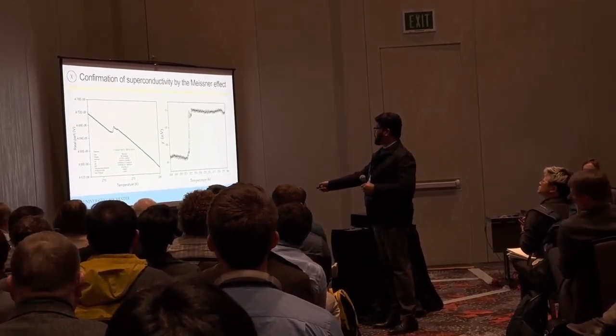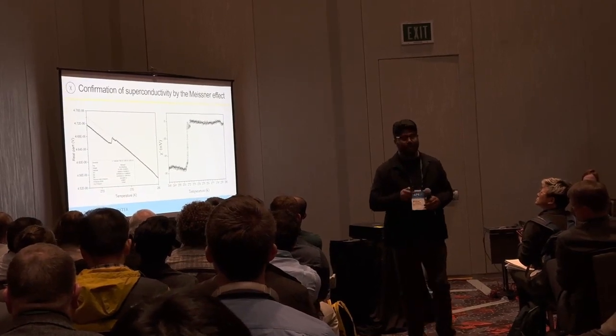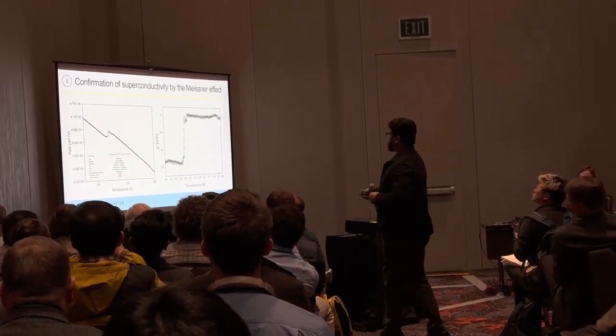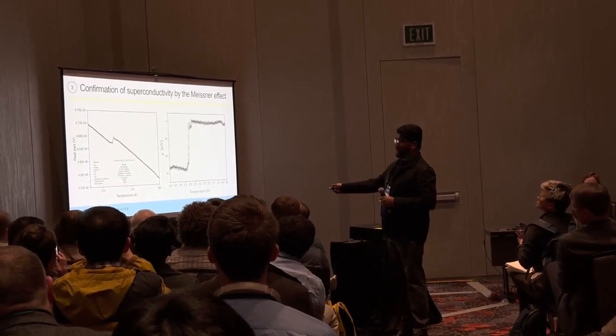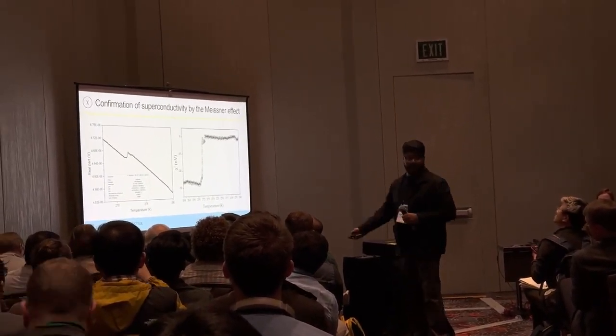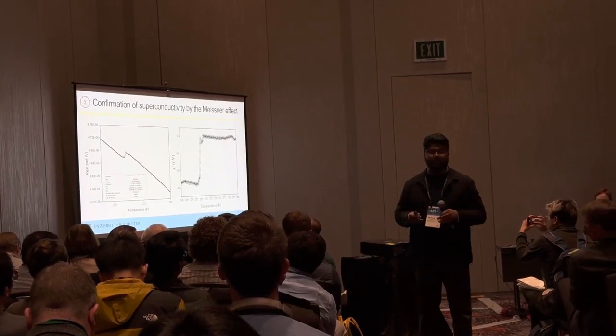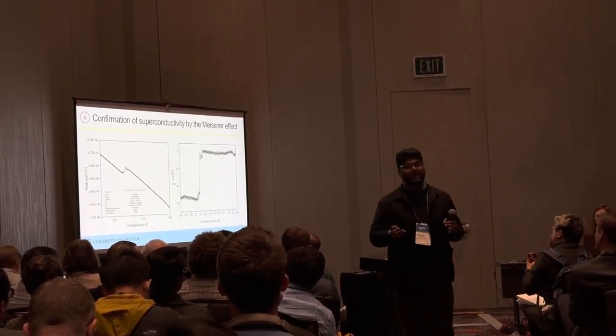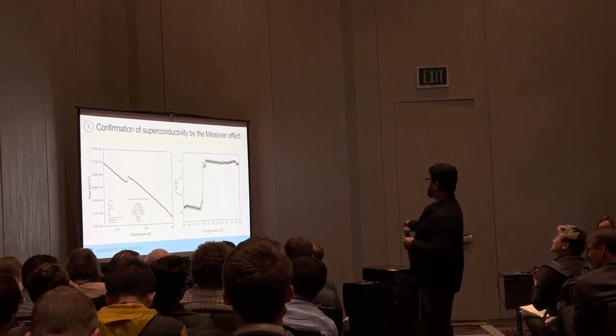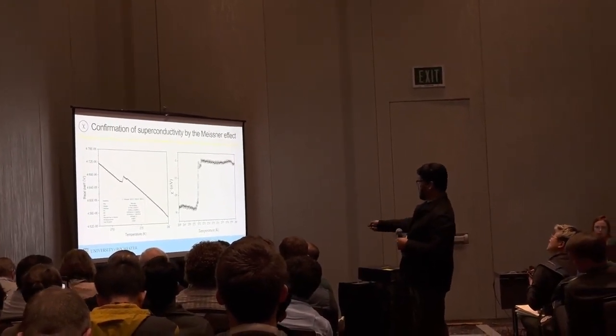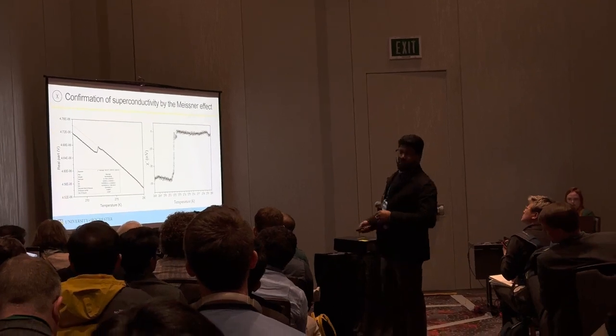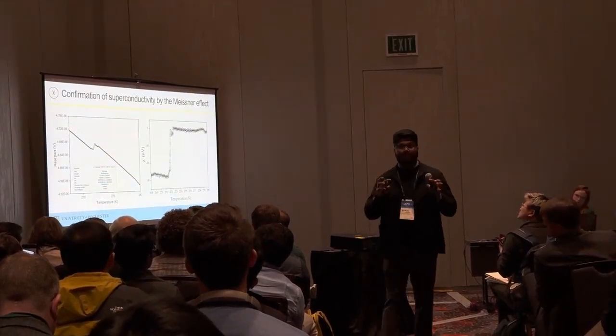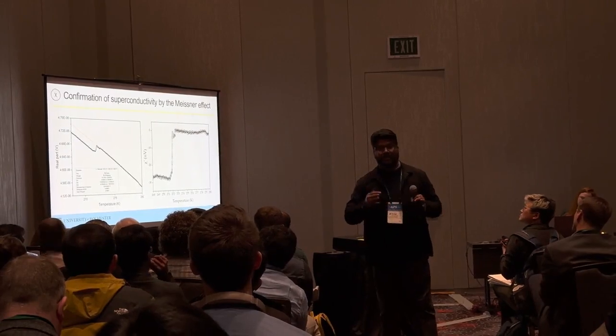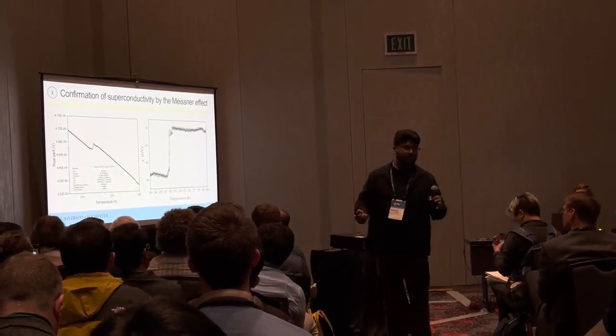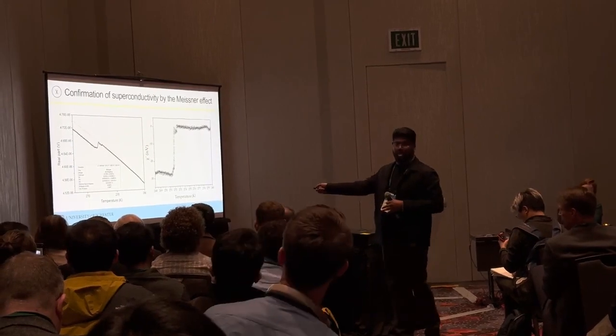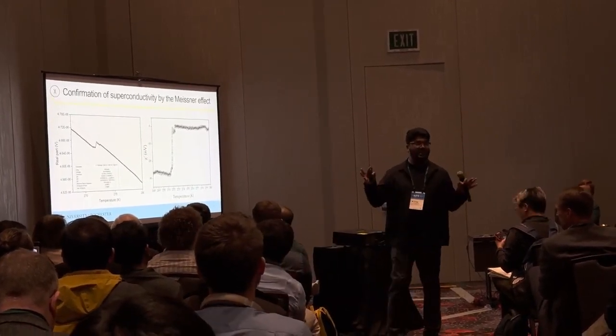What you see is the superconducting transition with temperature on this red lutetium sample. Cool it down, you see the signal dropping here, but you see this background rising. So there is always a background. You have to subtract it out to see the ideal situation. Once you subtract out this background polynomial, you see this graph. Again, this is purely for visualization. You can see this even without background subtraction, the signal is right there.